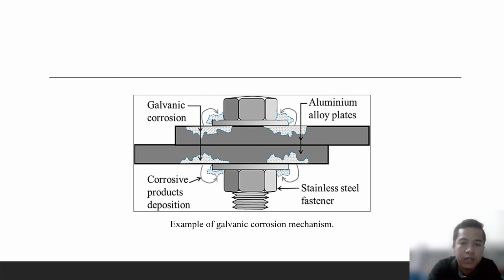If you can see, there is no gap between the two metals. There is an aluminium alloy plate, and then the nut is a stainless steel fastener. So this type of corrosion satisfies the three main points for galvanic corrosion to occur. If you can see, there is corrosion product deposition under the plate between the nut and the aluminium alloy plate. So this can cause galvanic corrosion to the aluminium alloy plate.